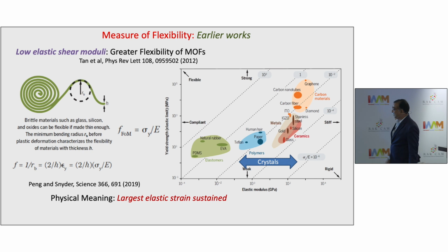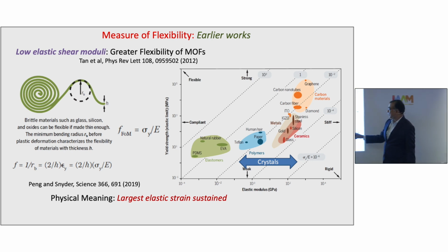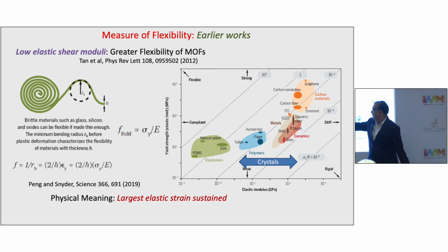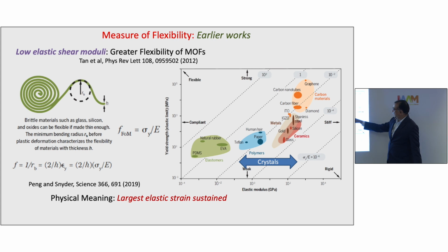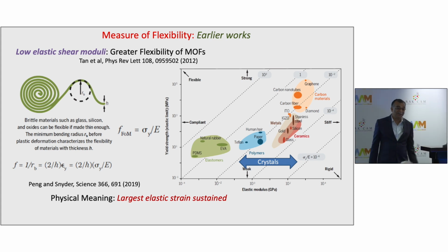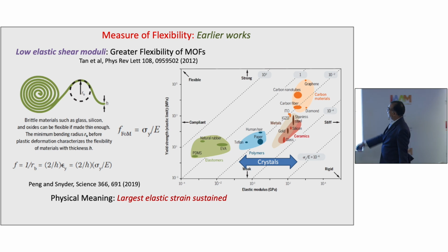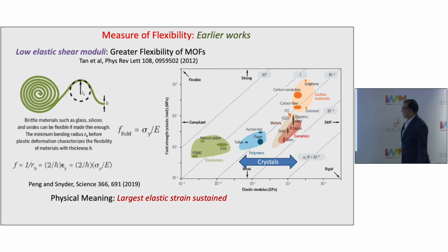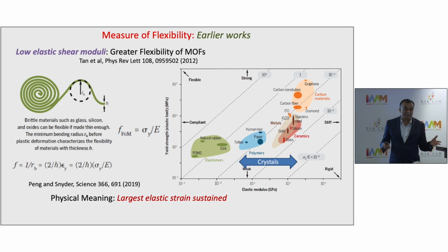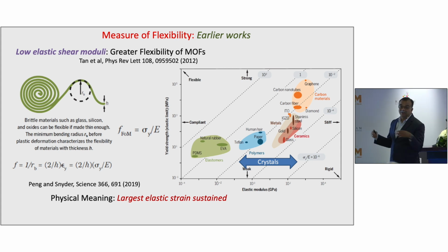Okay? So here is an Ashby type chart based on this work by Jeff Snyder and his collaborator. As you can see, the chart basically is dominated by non-crystalline systems in a way, because you will see this is the figure of merit for flexibility defined by them as sigma y by E. And you will see crystals and ceramics, basically metals, are here. They fall between 10 raised to minus 4 and 10 raised to minus 2, which means they are much less flexible in comparison with rubber, natural rubber, or even graphene or carbon nanotubes. So our goal is to understand flexibility in this window of systems, where they have a different mechanism of being flexible, and that's what we will uncover here.